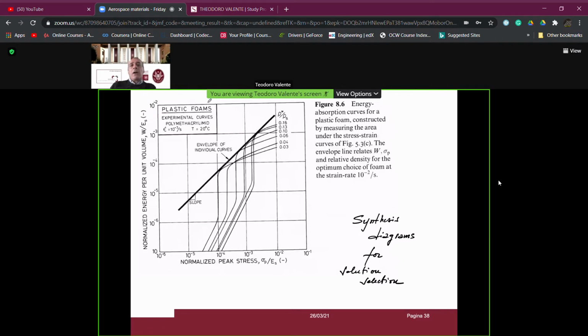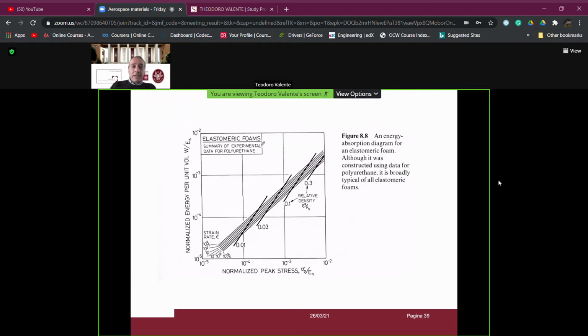This is a case of a plastic foam, that is a cellular material for which we have to consider as peak stress the maximum stress for the yielding of the material itself. And thus we have these final diagrams like those I showed to you. This is for polyurethane foams, elastomeric foams, and you see here, depending on the relative density and depending on the value of the strain rate, we have all the relationship between the energy which can be absorbed per unit volume and the corresponding peak stress.